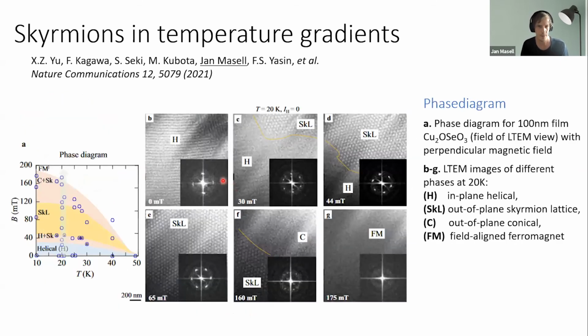And to prove this, we actually measured this phase diagram for the thin plate part of our sample. And there we see these Skyrmion lattices. Then we can say, by measuring the phase diagram, where we should position ourselves here in this temperature magnetic field phase diagram to see isolated Skyrmions or Skyrmion clusters inside a conical or polarized background. I hope that answered your question. Thank you. Thank you for that.